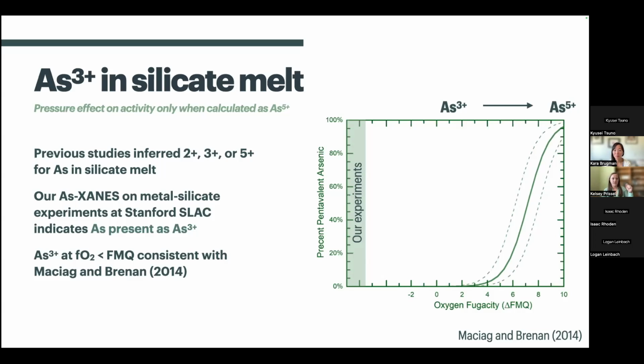observations, previous studies. You can look at the partitioning as a function of fO2, and the slope of that relationship can help you back out the oxidation state. However, in silicon-bearing systems, like these silicon-bearing metals, that method of estimating the oxidation state kind of breaks down a little bit, which is why there start to be more questions. And so it was really nice to look directly with the XANES method to answer this question. Arsenic in particular was one that I found in 3 different papers, all saying 3 different oxidation states for their calculation. Whereas for the other elements, usually there's one that everyone agrees on.